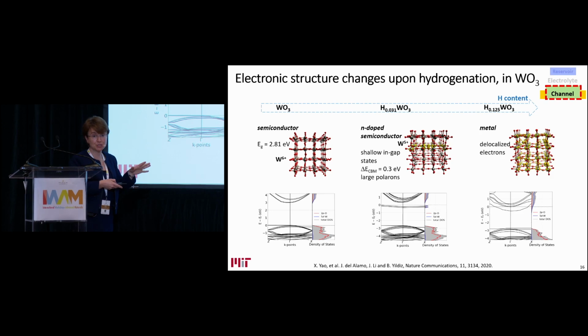So let's go back to the channel and what other alternatives do we have here. I already mentioned this briefly. For tungsten oxide, it's a semiconductor. When we insert hydrogen up to a few %, it serves as an N-type donor, which fills shallow in-gap states and forms large polarons. If you continue to increase the hydrogen concentration above 10%, the electronic structure is delocalized electrons, so here it's no longer very sensitive. You want to stay in as low concentration as possible.